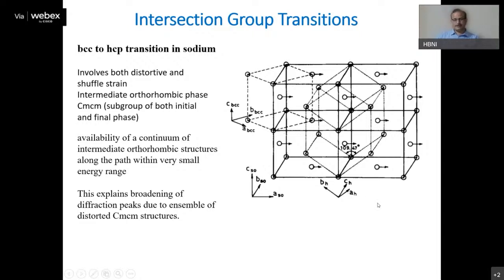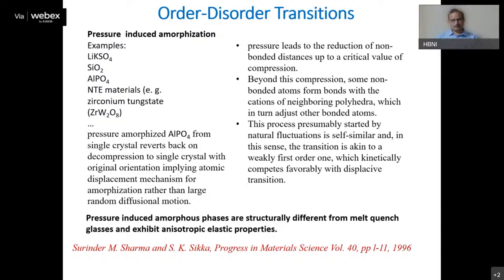So this way we can understand the mechanism of phase transitions and also try to describe these phase transitions with the Landau theory. Of course, one more case is there, the order-disorder phase transition. In this case, the daughter phase is an amorphous phase. Energetically, an amorphous phase should not be a stable phase, so in a sense it should not be a thermodynamic phase transition. But still, we observe this order-disorder phase transition in many cases, like in lithium potassium sulfate, in silica, in AlPO4, and many of the negative thermal expansion materials like zirconium tungstate.